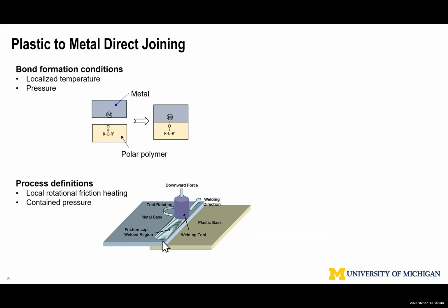So what it's doing is producing friction heat that propagates to the interface, right? You can do laser if it's transparent. That would be laser coming from the transparent side. You can do induction, and you can tune the frequency so that the heated region is on the interface. And this one produces a pattern, sort of like a friction stir, but in reality, it's not friction stir welding because you don't do anything to the interface, but the heat gets there. By definition, this little cylinder also serves as pressure containment, producing a local pressure vessel effect. And then during that process, heating, pressurization, and then you finish welding.